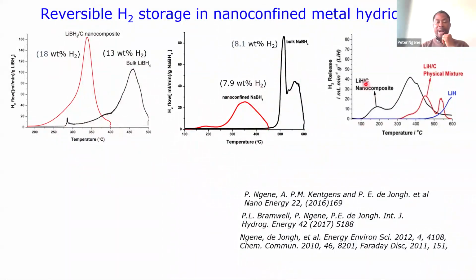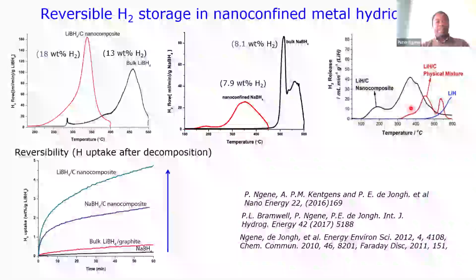And if you go for lithium hydride, just pure lithium hydride, if you want to get hydrogen from lithium hydride, you need to go above 600 degrees centigrade. However, if we just confine it in carbon, you already see that even around 100 degrees centigrade, you can begin to release hydrogen. So this nanoconfinement makes a great impact on the properties of this material.